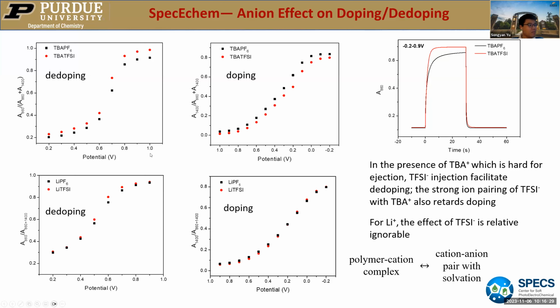When we have lithium, the difference is smaller. Even for the doping process, they just overlap. When we have a lithium cation, which is easier for de-doping, the contribution from TFSI is kind of negligible. So it's a complex energy consideration of the polymer-cation complex and the cation-anion pairing with the solvation. We also compare their kinetics. We can see when we have TFSI, the de-doping kinetics is strongly enhanced.